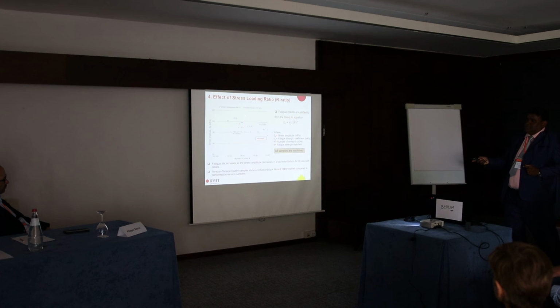The last point is the effect of stress loading ratio, which we already know well. We did tension-compression and tension-tension. There's a fundamental story here. Of course, you can see tension-tension gives a lower fatigue life than tension-compression, with a log-linear curve with a Basquin equation. Now, why does this ratio effect happen? Again, we looked at the fundamental scale and looked at the CT scan data, and showed that after the tension-compression test, which is R = -1, the pores are closing. Some of the pores disappear due to the crack closure effect, which gives you a higher fatigue life.